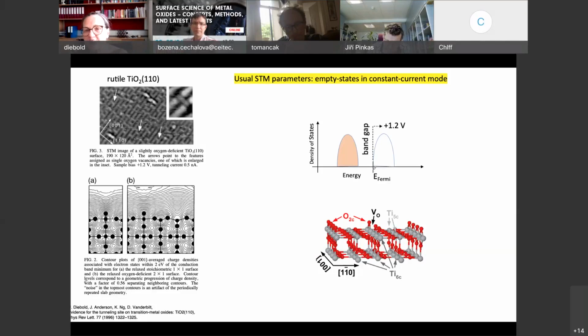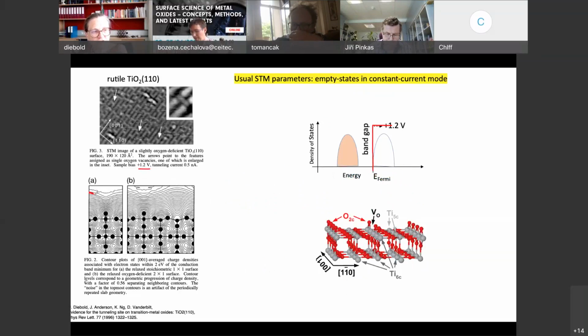Maybe this becomes clear. You have the Fermi level we set here. We bias the sample with plus 1.2 volts. That means the tip sends electrons into the sample, but it can only send them into these empty states. Then when we move the tip across the sample and keep this current constant, we put the tip here at a certain tunneling current. We move it in the X direction, then we come across this oxygen atom that sticks out a little bit. Here, locally, we have the oxygen states. Oxygen has no empty states, so we cannot put any electrons in, so we have to move closer with the tip to keep the current constant. And we move back again.